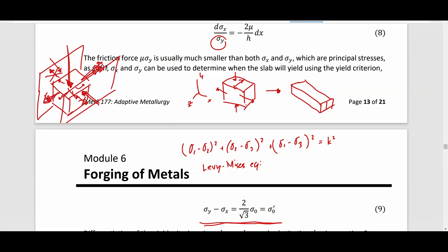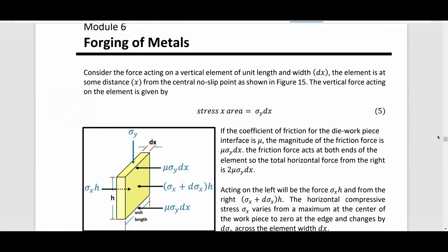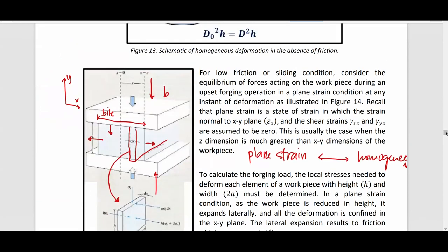Okay? So that being said, if open die actually siya, so kunwari wala tong harang na to, ang magpre-prevent sa kanya to flow outward is actually yung frictional forces, no? Because if you take a look at it, the upper side, this is in contact with your metal. Tama? So gusto mo mag-flow ng material mo dito and gusto rin niya mag-flow papunta dyan and doon sa opposite na z direction, no? Pero because of frictional forces, and you can actually compute this, kung enough ba yung isang frictional force to prevent it from flowing, meron tayong parang condition mamaya, no? Pero just try to imagine yung clay mo ulit.